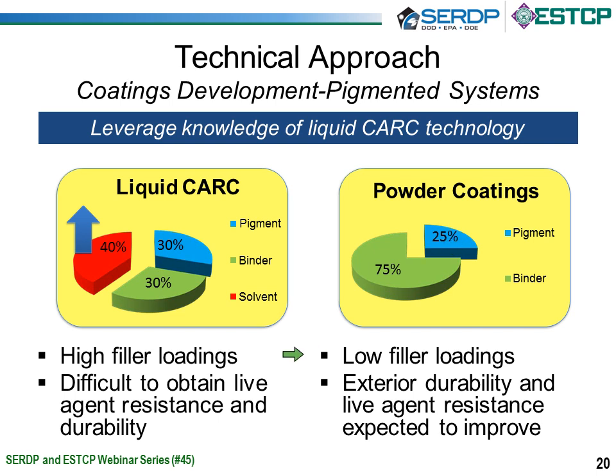So we're talking about low filler loading levels, and what this would lead to would be improved exterior durability and somewhat of a film that's more tightly formed, less filler pigments in there, which sort of act as a wick in absorbing some of these agents. And we had some background on this. We knew that powder coatings could be made flat with lower loadings of fillers, but we weren't able to meet all the requirements of CARC.